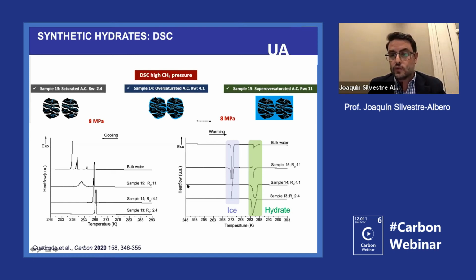So when we do the warming, we have 8 megapascals of methane, and we have 4 grams per gram of water, and we are melting the system. You can see that there is nothing of ice in the calorimetry experiment. Everything is just gas hydrate. So this is showing that under these conditions, carbon is able to convert the whole amount of water into gas hydrate. And of course, the same happens if we go to 2.4 grams per gram of water, if we are under saturation conditions.